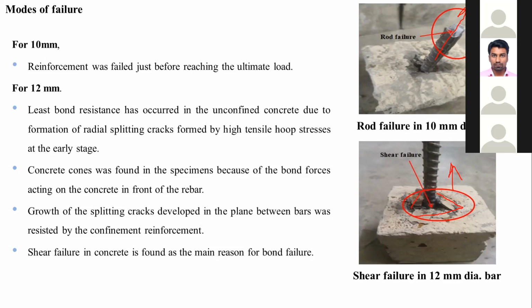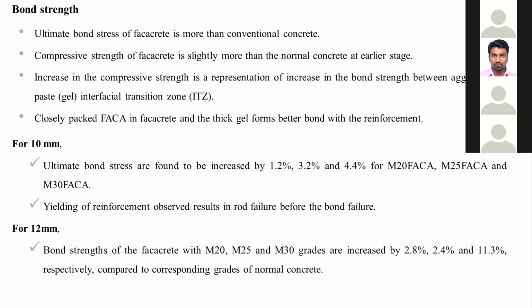Next, we find the bond strength. From the slip behavior, we found that the ultimate bond stress of the concrete is much more than conventional concrete. And the increase in the compressive strength is a representation of the increase in the bond strength between the aggregate and the interfacial transition zone. If we use facacrete, the aggregates will have more bonding than conventional quartz aggregate.